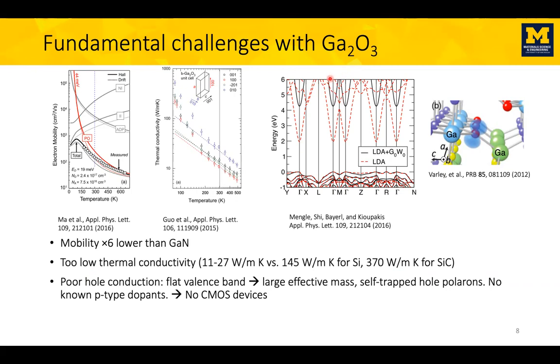So if you look at electrons, the bands are quite parabolic. The black solid lines are the more accurate methods. And so these parabolas are good, which means that the electrons here have a light effective mass. But if you look at the valence band, the occupied states, you see that they're flat. And that's a bad sign because it means that holes have a hard time transporting in this material, and they may even get self-trapped and form these polarons that you see here. So a hole will localize the lattice and will trap itself within its own distortion. As a result, there's no p-type conductor, there's no p-type dopants, and as a result, you cannot make CMOS devices.